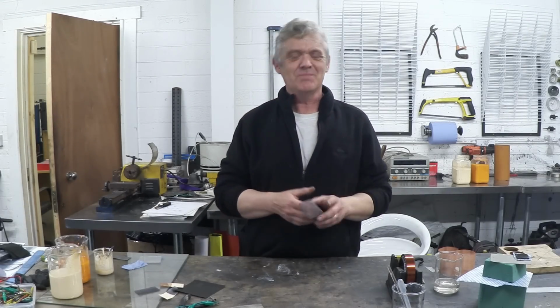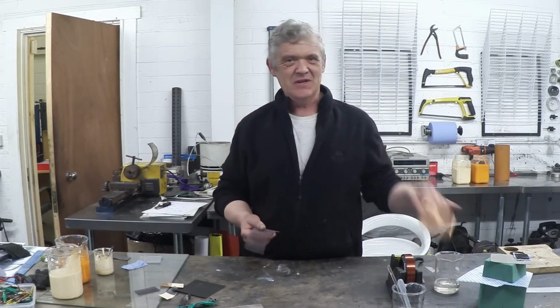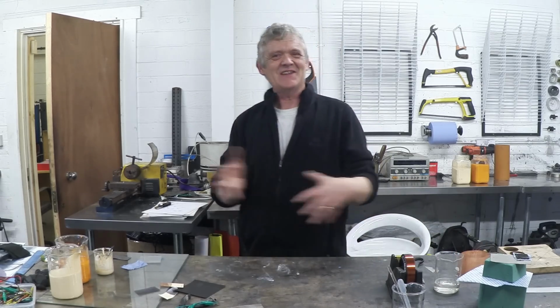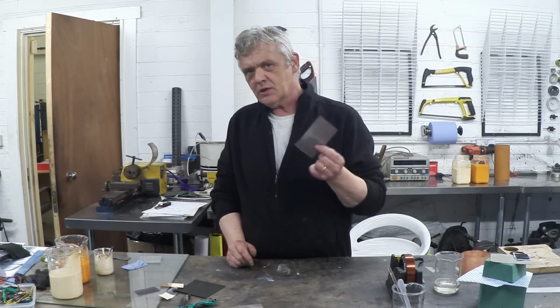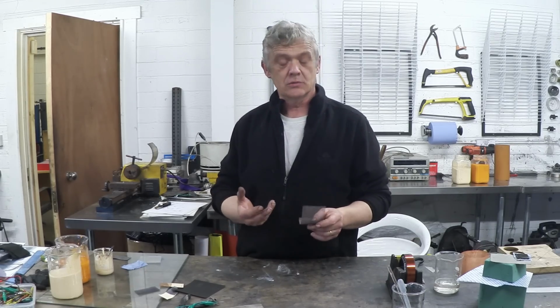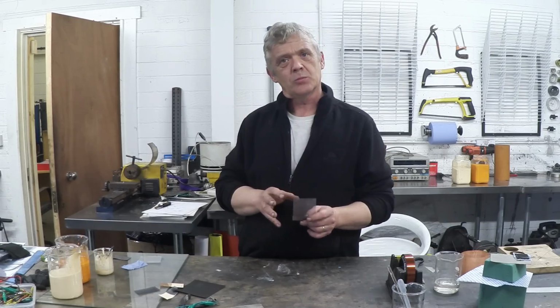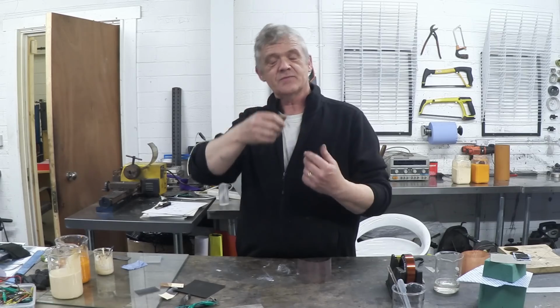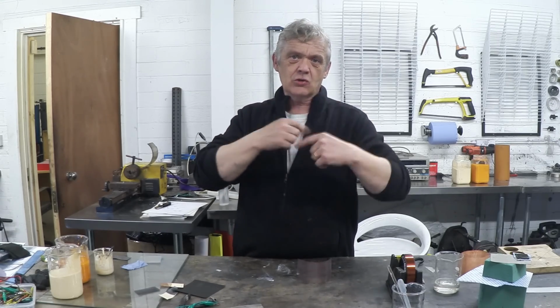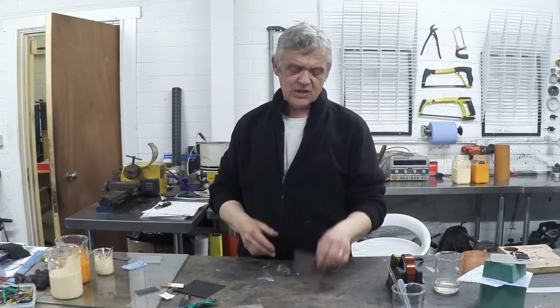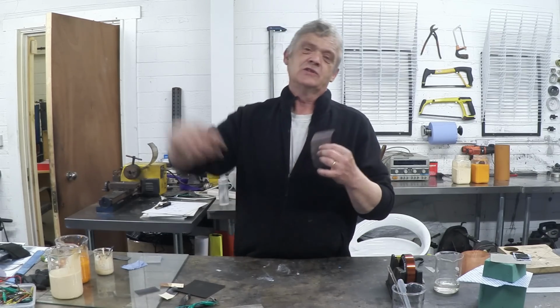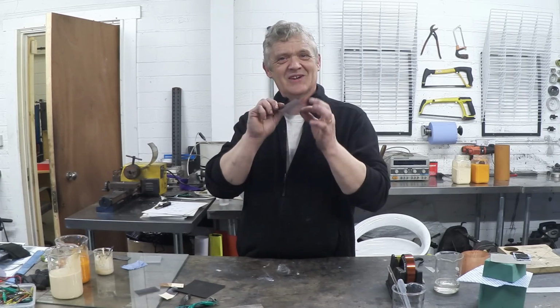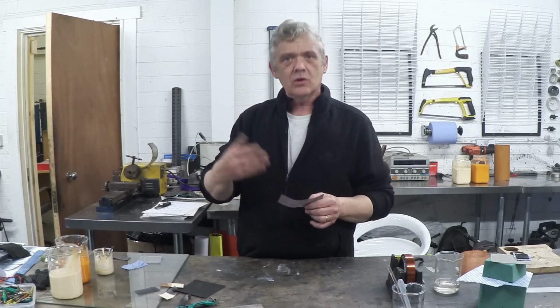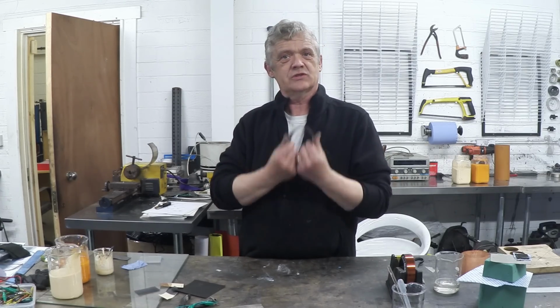So getting the material was a bit of a challenge to do a video on, because how interesting can that be? We cut a bit of that off and we put it in the oven and out comes that. So kind of difficult to demonstrate that really effectively. But what we've done is we've taken a better quality material and we've given it a process that's far more controlled. Now, at 400 degrees centigrade, there's a tendency for red copper oxide to form, but to form in nanocrystals. So they grow out as little hairs. And they're on a wire, so that wire is obviously a circle, and they grow out from that circle perpendicular to the surface, a bit like an urchin, so lots of points sticking out like that. And they stick out all over that surface, and that surface is relatively transparent. So the sun can get in there and do its job. And those urchin cores have all got a copper centre to them that's all joined up and coming to the edge here. So having a slightly better material with a more controlled process, what we should get is a device that works much, much better.